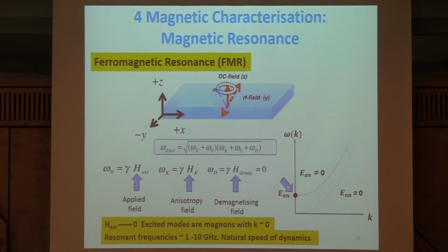So the energy of this magnon in the limit of low field and low k is the same as the ferromagnetic resonance absorption frequency. That makes sense, because if you're trying to drive it with photons, then the ratio of energy to k is very large, so they can only really excite down to the limit of very small k.